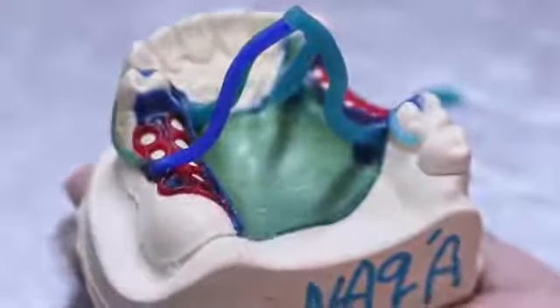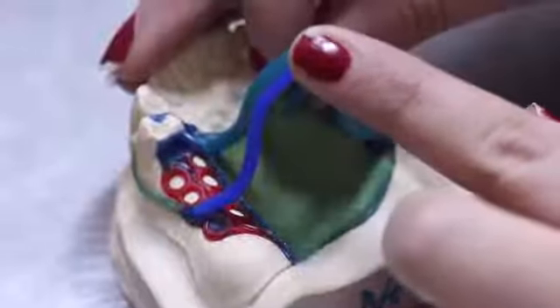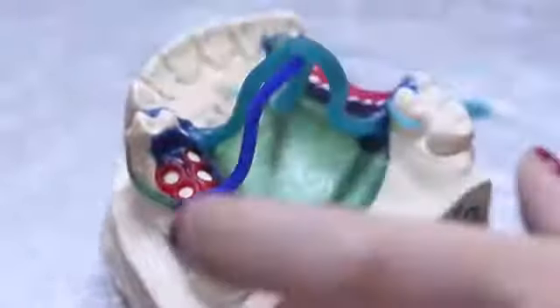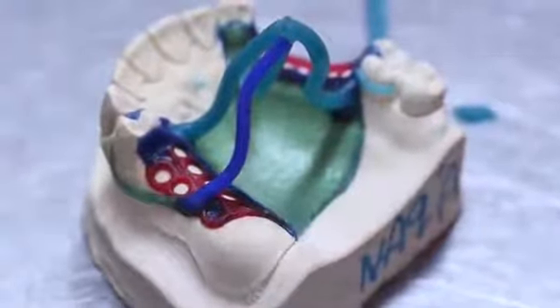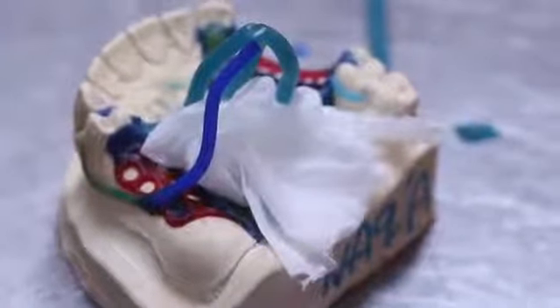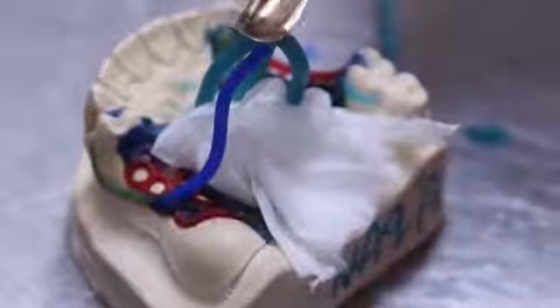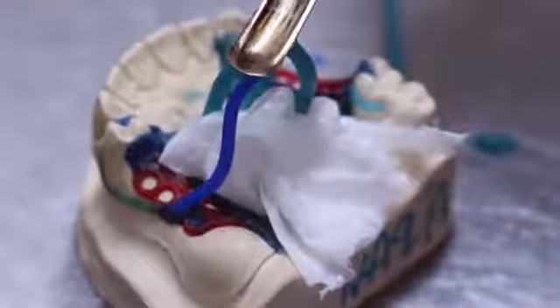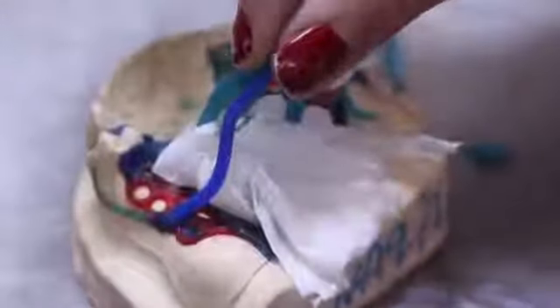The ideal area for the sprue former is the point of greatest bulk in the pattern, to avoid distorting thin areas of wax during attachment to the pattern and permit complete flow of the alloy into the mold cavity. Any area that is separated from the bulk of the framework by a long span of lattice work or meshwork requires a secondary sprue former. These secondary sprue formers should be 1/3 to 1/4 of the diameter of the main sprue former and should be gently curved. A reservoir should be added to the sprue network to prevent localized shrinkage porosity.